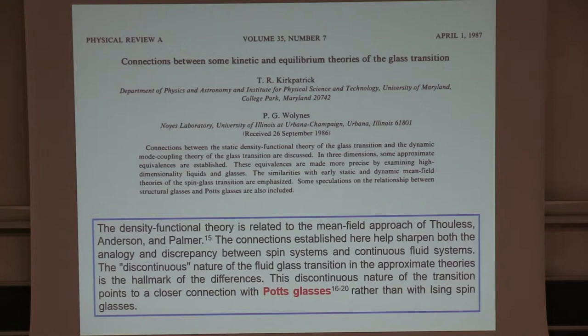And so this is the first paper we wrote from that Aspen encounter. It has many interesting ingredients. One was we could show the theories were equivalent, but only in very high dimension. Now that's sort of to be expected, because mode coupling theory and density functional theory are both approximate theories. So it could only be that in some special limiting case could they be the same. Even then, they were not quite exactly the same in high dimension, but they were very close. They both agreed that the transition was discontinuous in some fashion.